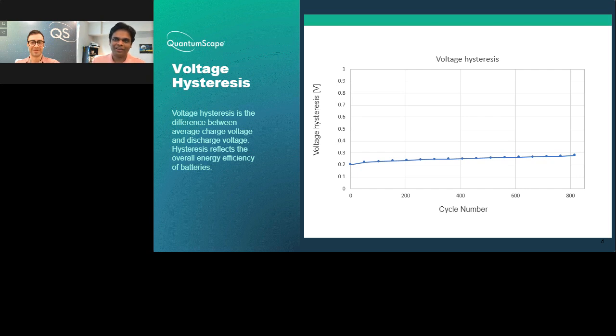Yeah, maybe I'll add some color here. I think there was an excellent paper by Jeff Dahn reporting a wide range of tests on their really high quality lithium-ion cells, and this is one of the metrics that Jeff asks to report in that paper. And the key point here is that the voltage hysteresis that we have here shows that the batteries are about 95% efficient. So it's losing about 0.2 volts over sort of a 4-volt cell.